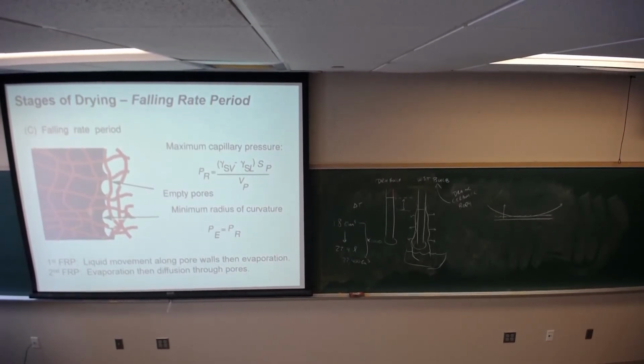Now that's going to suggest that you can create damage in drying. Fair enough, you can, okay? But if you increase ionic strength, then in fact your drying stresses are dramatically reduced. Particles are able to rearrange more efficiently. Otherwise the system is locked up and unable to rearrange. That can create some problems for us, okay? So having salt in the water of some form or other, some ionic strength in the water, is beneficial to drying.